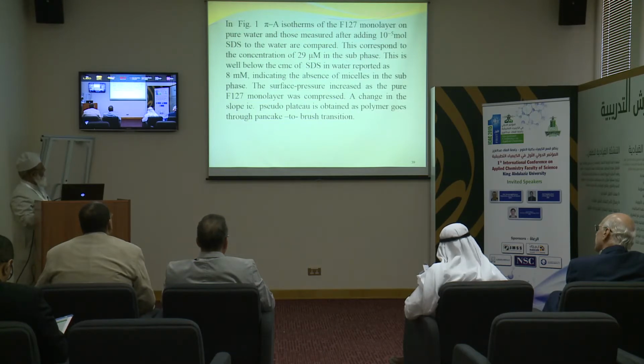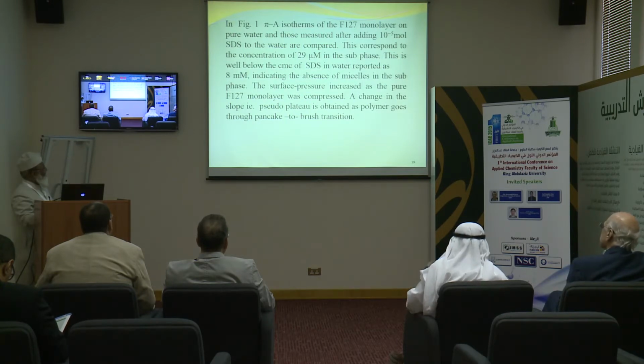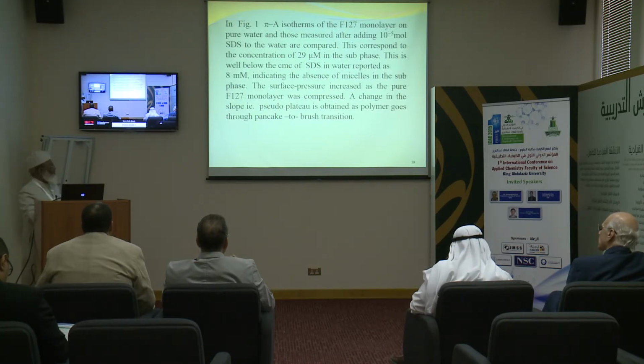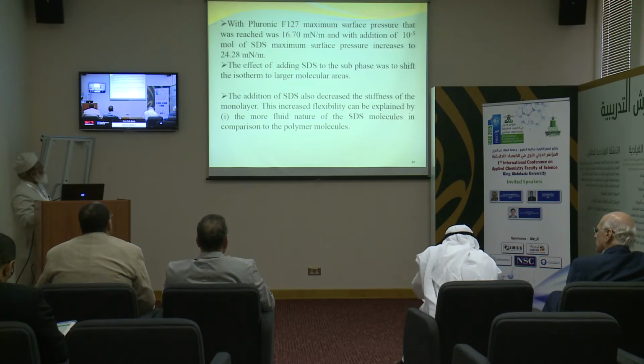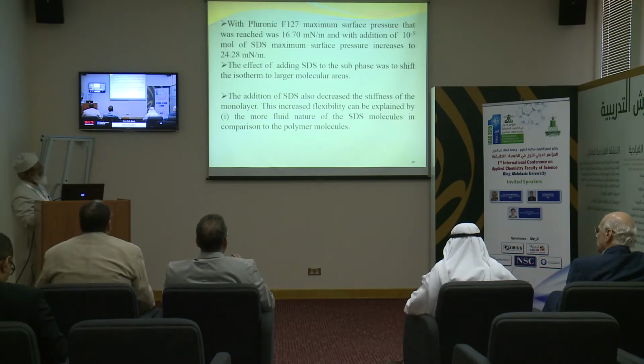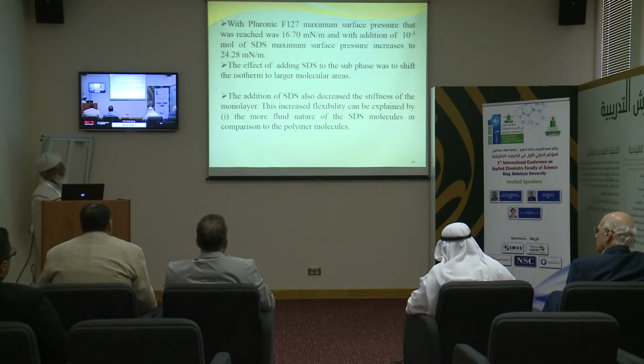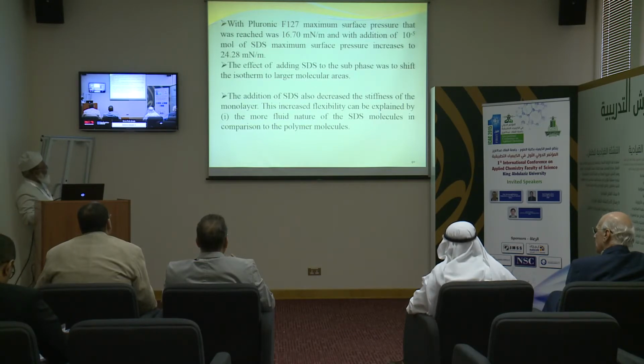The surface pressure increased as the pure monolayer of the polymer was compressed. A change in the slope, that is a pseudo plateau, is obtained as the polymer goes through the pancake to brush transition. With pluronic, the maximum surface pressure reached was around 16.7 millinewton per meter, and with the addition of 10⁻⁵ mole of SDS, the maximum surface pressure increases to 24.28. The effect of adding surfactant to the surface was to shift the isotherm to larger molecular areas. The addition of surfactant also decreased the stiffness of the monolayer.